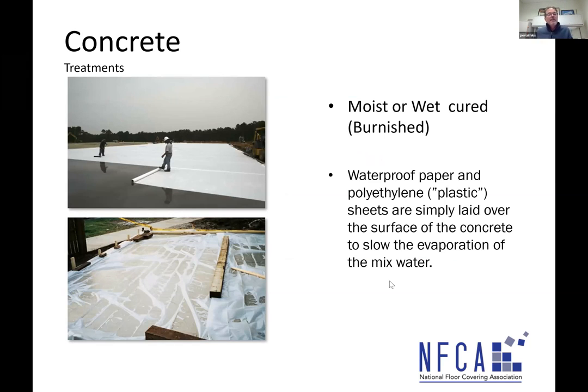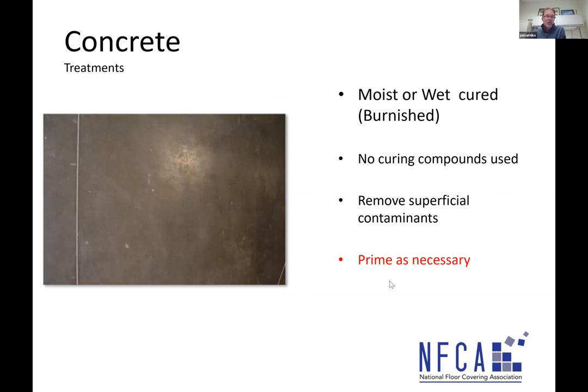So if we have concrete that is wet cured with a polyethylene sheet, plastic, something like that, no curing compounds used, no liquid sprayed on curing compounds. From a prep standpoint, we need to remove superficial contamination, drywall mud, paint overspray, things like that. But we don't necessarily need to mechanically clean to create absorbent or profiled concrete. There are some patching materials that stick directly to clean, burnish type concrete, and there's some leveling materials that can adhere to that with appropriate primer, two-component epoxy type primers. But the bottom line here is you check with your manufacturer for the specific recommendations.